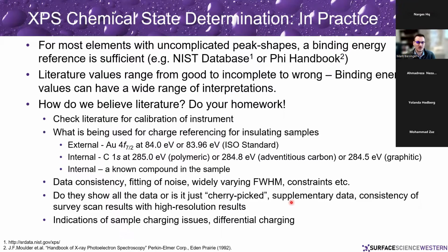Some of the things that you should check for when you do look at literature: is there detail about calibration of the instrument? What sort of charge referencing has been used? And we'll talk about charge referencing a lot later on. Look for things like data consistency. We're seeing a lot of people fitting peaks to noise, widely varying full width half max, no constraints on their curve fitting, those sorts of things.